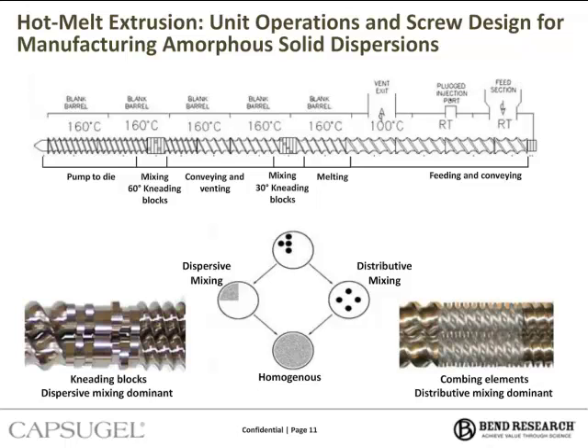Now the 4th unit operation is venting. And here the purpose is simple. It's just to remove residual moisture and gas or air entrained in the powders. And a vacuum can be used to assist. And finally, the 5th unit operation is extruding, extruding the dispersion out of the die. And as you can see at the end of the screw, we have special pumping screw elements used to create pressure to flow the extrudate out of a shaped die.